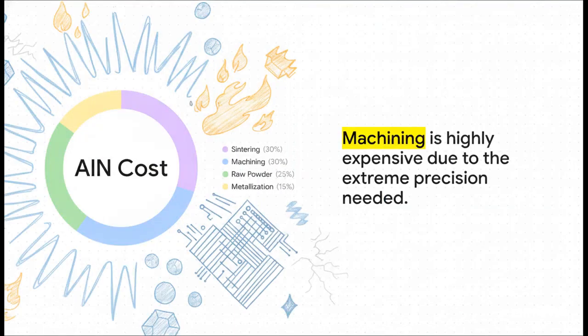Beginning to end, yeah, not cheap. If you look at the manufacturing cost for premium aluminum nitride, sintering at extreme temperatures takes up 30% of the cost. The ultra-pure raw powder, that's another 25%. Metallization takes 15%. But notice that machining takes a massive 30% of the cost. Diamond grinding a brittle material perfectly flat, without introducing any of those catastrophic Weibull cracks we talked about earlier, drives the price up enormously. You are paying a premium for extreme precision.